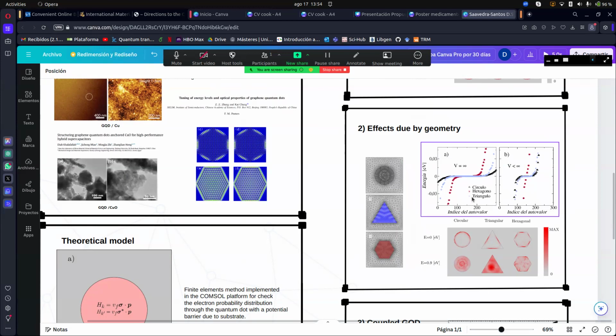However, when the substrate is added, the hexagonal symmetry completely breaks the degeneracy that was previously observed, demonstrating that the geometry's influence significantly affects the energy behavior. Regarding the wave function density of states, it's observed that at the Fermi level, the behavior is similar to what was previously shown. The wave function localizes at the edge due to relativistic effects, and as the energy increases, the electron begins to localize within the graphene without showing any signs of quantum tunneling due to the electron's high velocity within it.